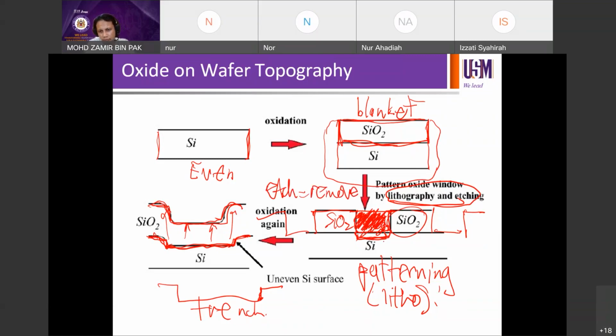So you can actually remove this silicon in the trench. So that's why you end up with silicon like this. So it was due to oxide that was patterned, and then silicon was then etched, and you get this trench. This trench is just silicon. Then after you've etched the silicon, you can then remove this silicon dioxide as well, and then this oxide here and here is no longer there. You will be left with patterned silicon only.